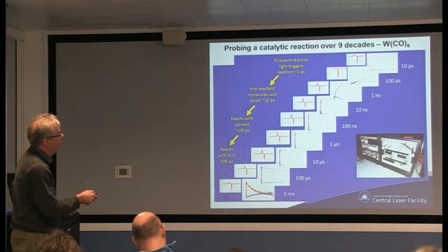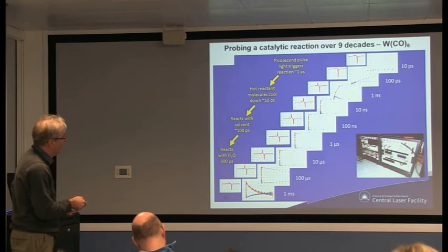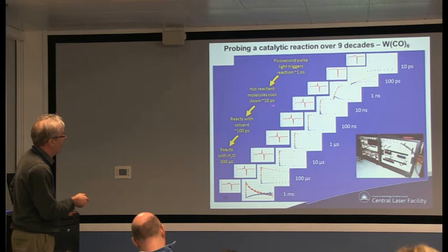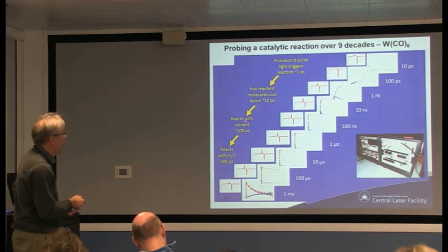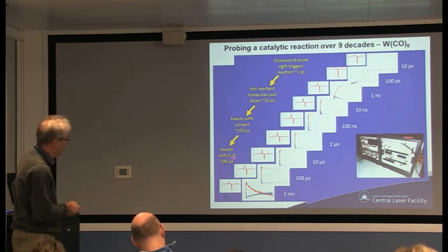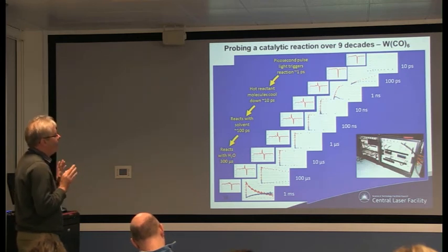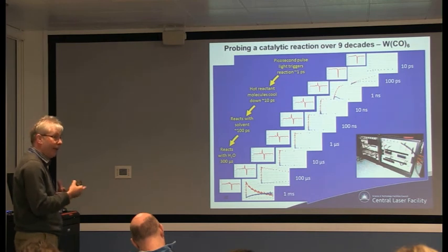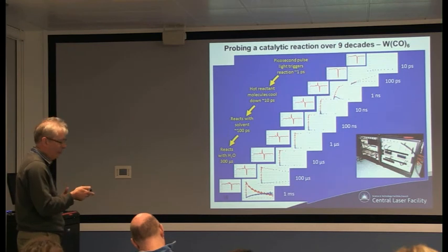This is what it looks like. This is with a tungsten carbonyl compound being probed. Effectively, these are the spectra we're getting from the kit. This is effectively what's happening. So we're basically triggering a reaction, watching the reactive molecules cool down on the 10 picosecond time scale, watching how it reacts with the solvent on the 100 picosecond time scale, and finally watching how the compound reacts with water on the 300 microsecond time scale. So again, this is all very fast dynamics, looking at some of the vibrational modes, how the things react, how the molecules change energy states.